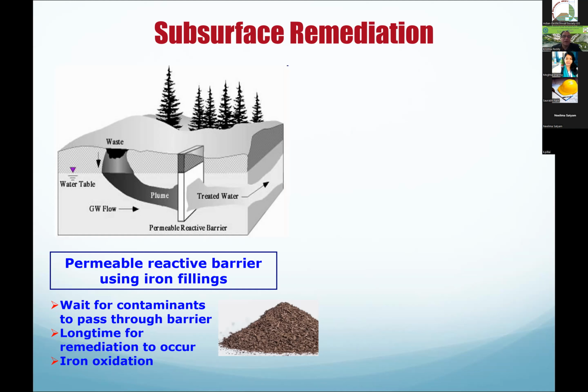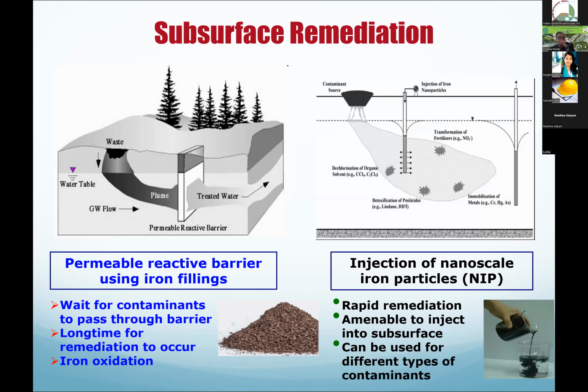But the problem is, as I said, it's going to take a long time. What happens if the hydrogeology changes? Instead of the plume coming through this one, if it bypasses, then putting this one in becomes useless. So that's the danger with this technology. The reason is that this is macro scale iron, so we have to put it in the trench. The macro scale iron looks like fine gravel or coarse sand. So instead of that, if I have nanoscale iron particles, then what I can do is put a well into the contaminated zone, and I can inject my nanoparticles.